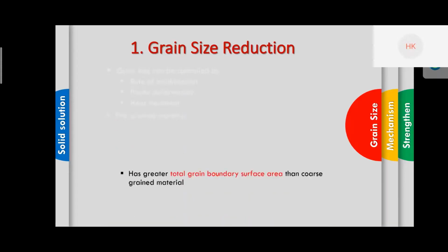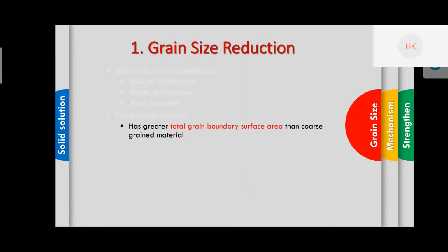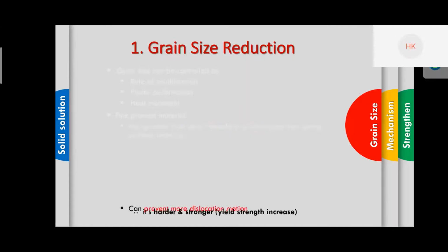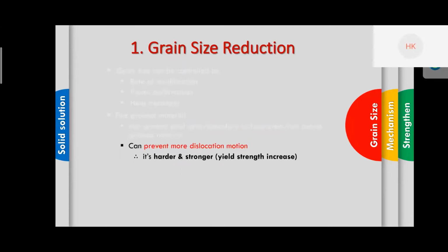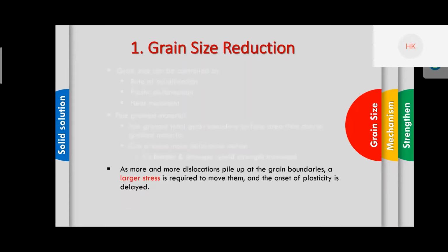Fine grain material has a greater total grain boundary surface area. If we have a very small grain size, that means we have a very short distance of dislocation movement, and finally it will be blocked by the boundaries. If we have a bigger size, the dislocation motion will have a very long distance. So compared to bigger size, the smaller size has a greater surface area that will block the dislocation motion, and finally we will produce a very strong metal. It can prevent more dislocation motion, and finally we can have a stronger material.